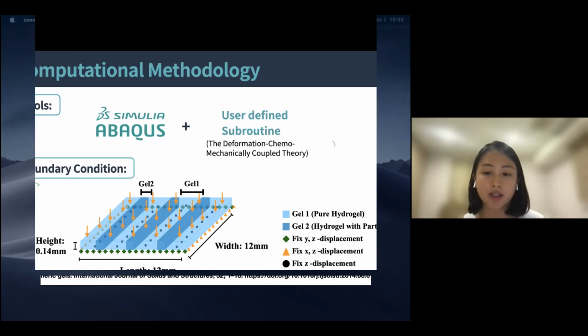And the restraint condition is quite complicated because it is based on the observation of the interaction between the hydrogel film and the electrode. The four edges of the film and the area in contact with the electrode, which is the gel 1 area, provide more adhesion to the film. So to capture this feature, the four edges of the model will be glued on the substrate, and the corresponding displacement in the relevant direction will be fixed in the current model.